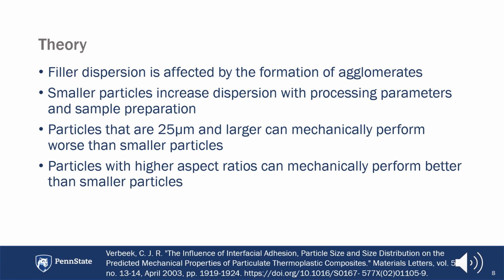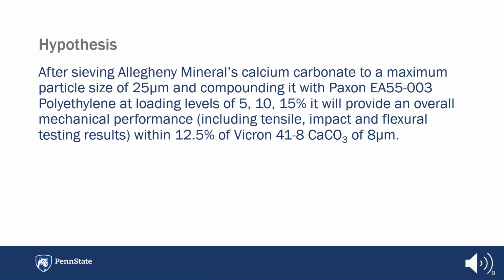And from this slide is how we constructed our hypothesis for this project. So the hypothesis for this project is after sieving Allegheny Minerals calcium carbonate to a maximum particle size of 25 microns and compounding with polyethylene at loading levels of 5, 10, 15%, it will provide an overall mechanical performance, including tensile, impact, and flexural testing results within 12.5% of Vicron 41-8 CaCO3 of 8 microns.